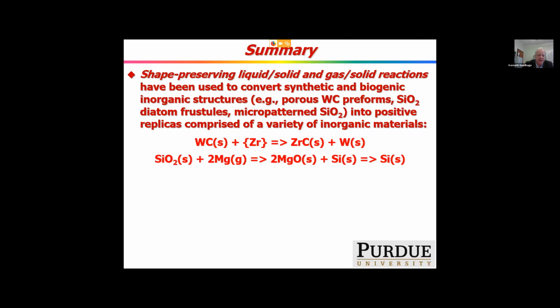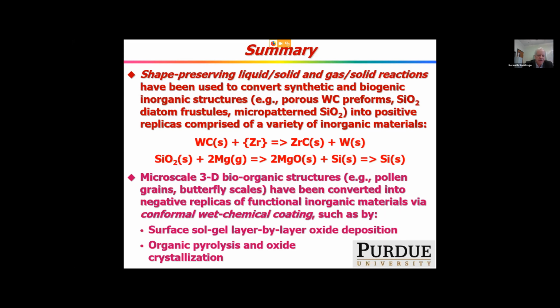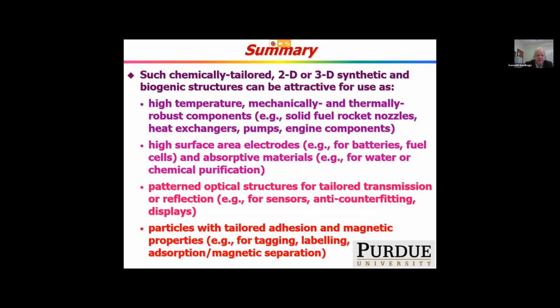So quickly then, I hope I've convinced you that we can take shape-preserving liquid-solid or gas-solid reactions, take synthetic or biogenic templates and convert them into ZrC-tungsten, for example, or porous silicon replicas, and many others too. We can take microscale organic or bioorganic structures like pollen grains or butterfly scales and use conformal coating techniques like surface sol-gel to deposit a wide range of ceramic chemistries and then fire them to make replicas. I didn't mention the metal coatings that we can do as you've seen as well.